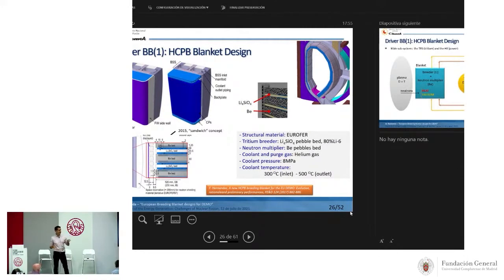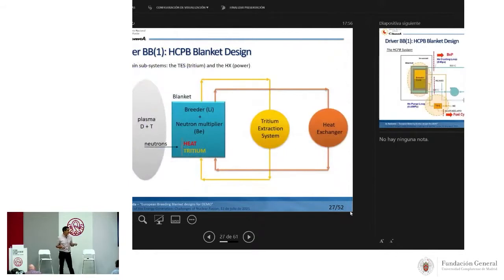In all the cases, the structural material is Eurofer, which is the reduced activation steel. In this case, the tritium breeder is lithium orthosilicate in form of pebble bed, and the neutron multiplier is beryllium. You can see in this picture that they are arranged in the form of a sandwich. We have a lot of beryllium, a small slice of breeder, and so on. The coolant is helium at 8 megapascals, and the inlet and outlet temperatures of this coolant are 300 degrees Celsius and 500 degrees Celsius.